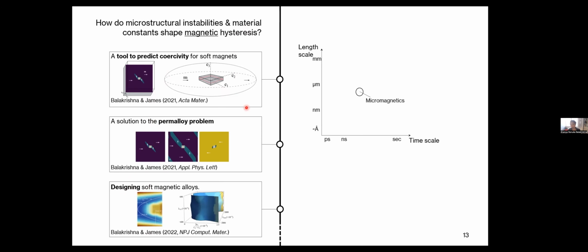So the overview of the work is we use micromagnetics theory, which is when we simulate microstructures of hundreds of nanometers length scale and at diffusive time scales. But we are actually, in fact, predicting the hysteresis of a bulk magnetic material. If anyone's interested, I'm happy to explain what this theorem means. Essentially, it gives you a unique way of splitting your field, so you can actually model a very large bulk ellipsoid and predict the hysteresis of a bulk alloy, just to eliminate any of the shape effects that you can get by having a small microstructure.